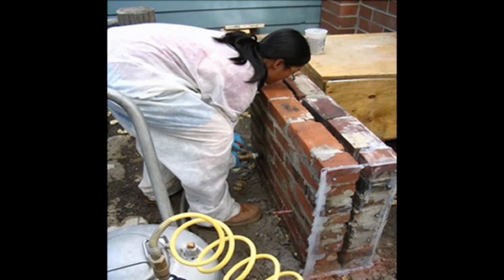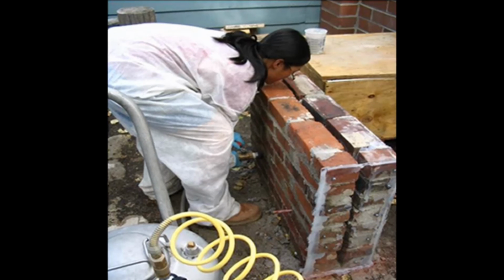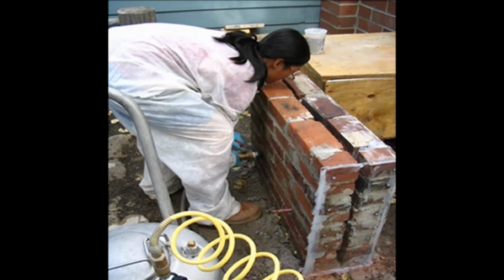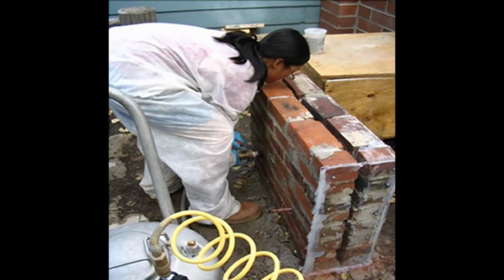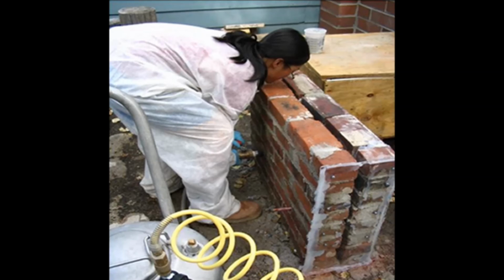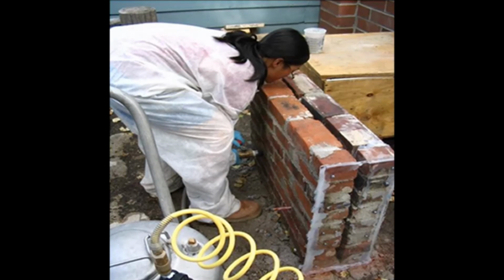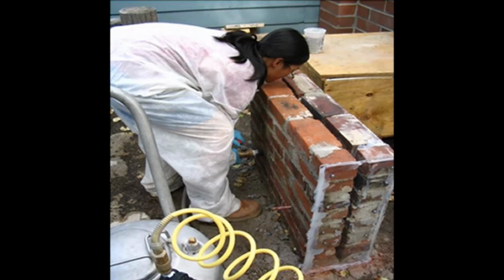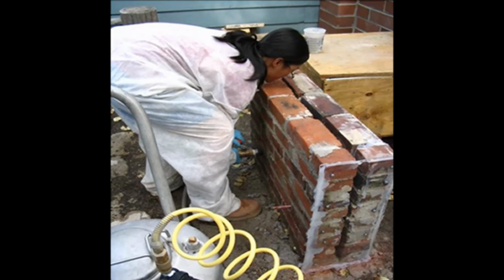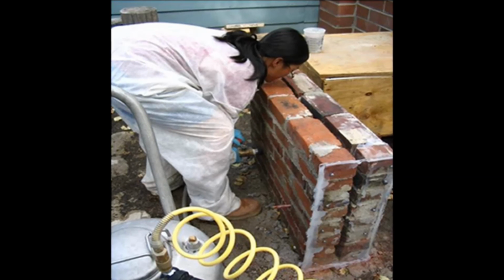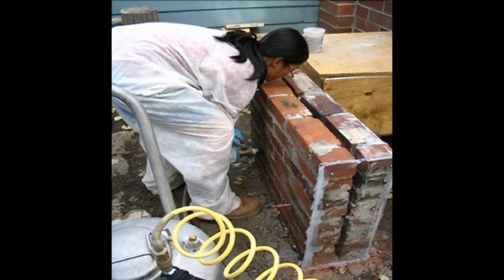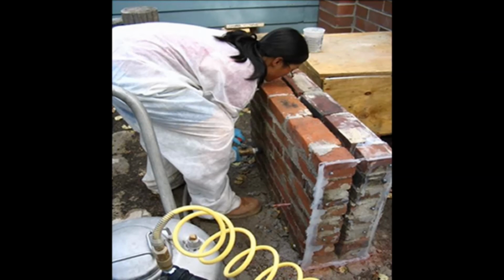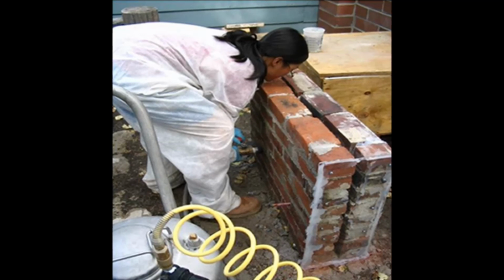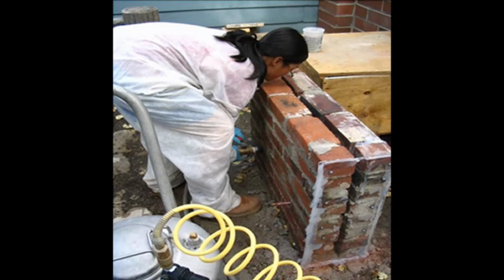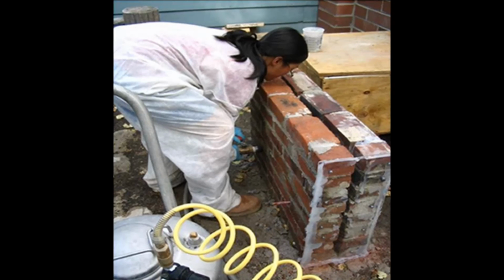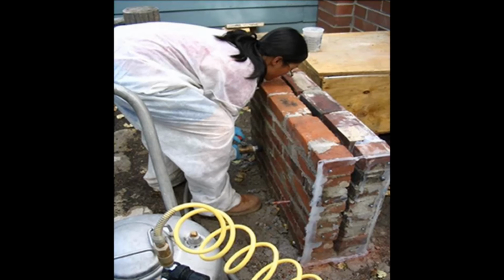So the results and the conclusion of the case study here resulted in 11,000 square feet of wall area being injected, 42 cubic yards of our CIF compatible injection fill being injected. That came out to about 7% of what the wall volume actually was. 9,000 linear feet of stainless steel reinforcement bars, and there were no visible changes to the structure and no service interruptions. And that was a very big deal there because they were not able to shut these pump stations down.